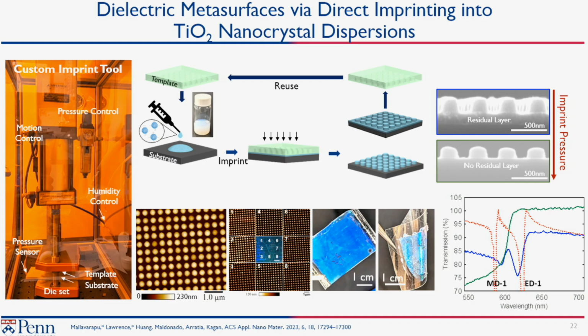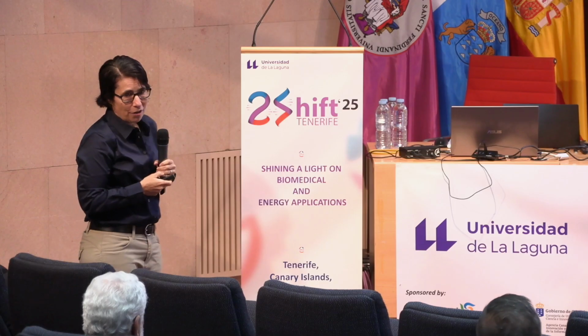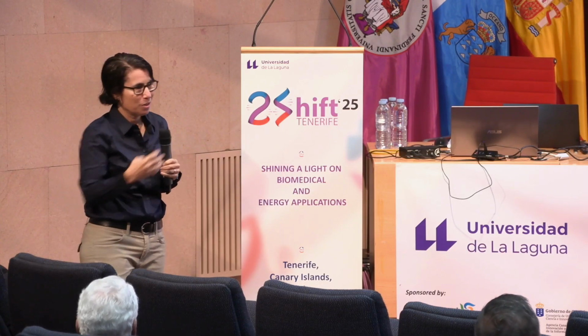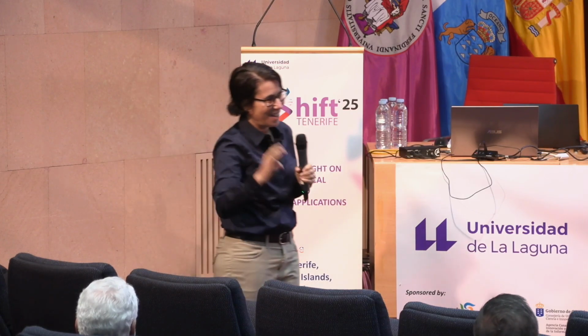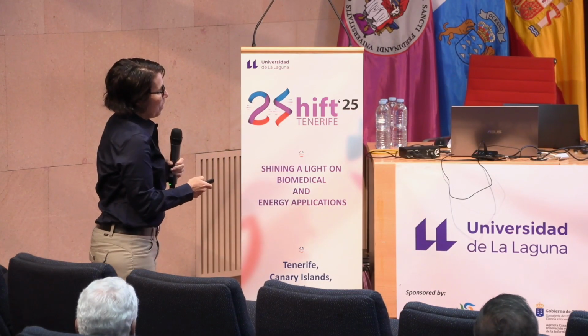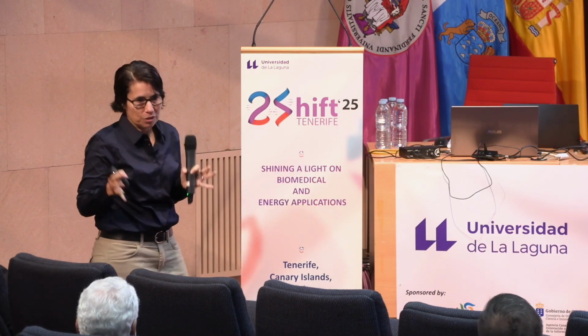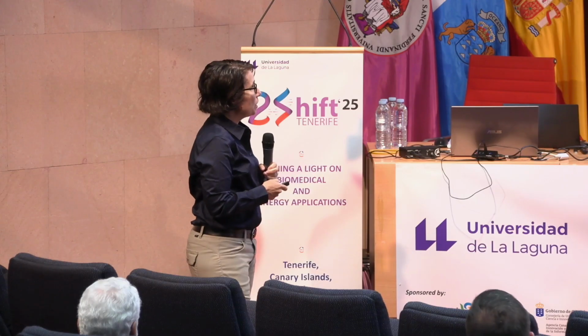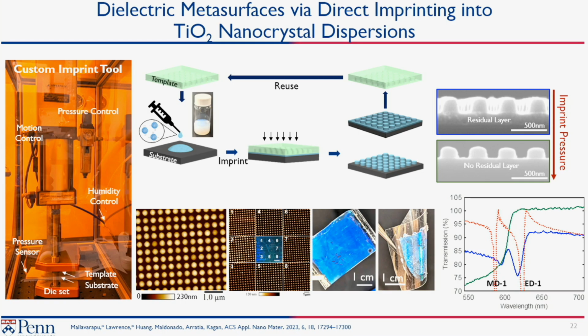Interestingly enough, we actually like the structure with the residual layer, for reasons of optics. But we learned that we could do this over very large areas. We've since moved from our home-built machines, for which we started to have all these clones, and then bought a commercial one and decided that was a better way to go. You can print on rigid, plastic, all sorts of substrates that you might want. And the difference is that if you have structures with this residual layer, you get these higher Q resonances, like you can see here in blue, compared to when you have no residual layer, where you see very little. So if you wanted to get good dielectric resonances, you had to make structures tall. But if you have this underlying residual layer, you don't have to make it as tall, which makes it much easier in fabrication and for stability.